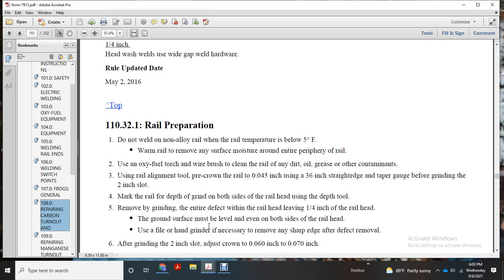Do not weld a non-alloy rail with a rail temperature below 5 degrees Fahrenheit. Warm the rail and remove any moisture from the entire periphery of the rail. Use an oxy-fuel torch, wire brush, or wipe to clean the rail of any dirt, oil, grease, or other contaminants. Align the rail with the tool, pre-crown the rail to 0.045 inch with a 36-inch straight edge and taper gauge before grinding the 2-inch slot. Mark the rail with the depth of the grinding on both sides of the rail head.